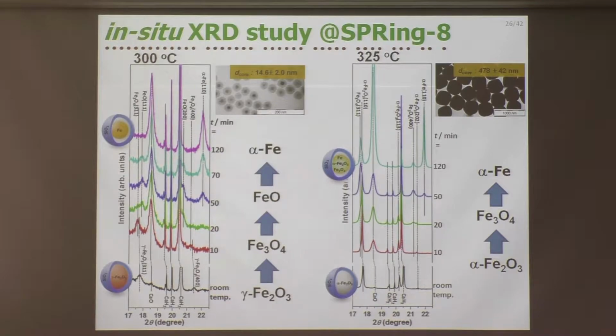Yes, it is very similar, but there are several differences. One of the biggest differences is the formation of the FeO phase. This was only observed in the smaller samples, probably because FeO is a metastable phase, and its stability increases with decreasing particle size. Since this sample has a very big particle size, the FeO is unstable and cannot exist.